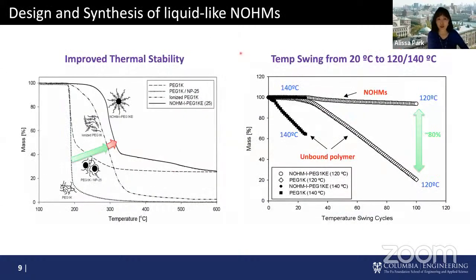So the next thing we really checked was, did we improve the thermal stability of these materials? On the left-hand side, looking at the thermal stability of different materials, untethered polymer degrades relatively quickly, at about 200 degrees C, particularly this PEG. But by tethering them, we can expand this thermal window by almost 100 degrees. But it becomes even more interesting if you look at the right-hand side figure.